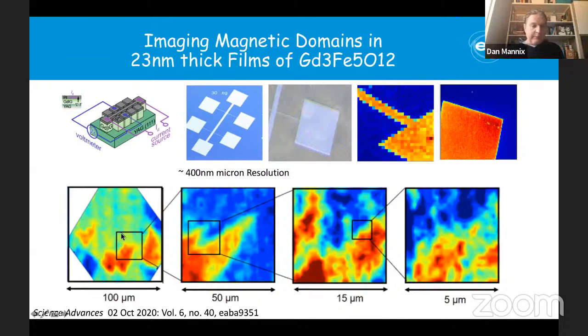Now, the bottom figure here shows the difference. This is the flipping ratio that I showed before, the circular flipping ratio. And we start to see some interesting contrast develop. We see positive intensities in the flipping ratio in red, negative ones in blue, and basically zero around here, which is green. And we can start to zoom into this.